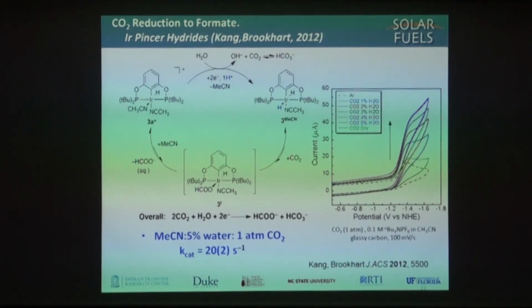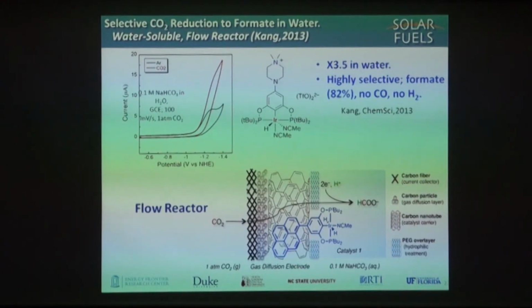And here you see catalytic currents as you add more and more CO2 to the solution. The rate constant is pretty respectable. This thing turns over in 50 milliseconds, so it's pretty fast. So that's observation number one. That's pretty good for the second CO2 reduction product, formate. But Pond took this two steps further. By putting on this ammonium tag, he could now make the catalyst aqueous soluble, and he did. And in aqueous solution he discovered, under the right conditions, that is, don't make it too acidic, it's very simple, that you can in fact reduce CO2 selectively to formate with no CO and no hydrogen.